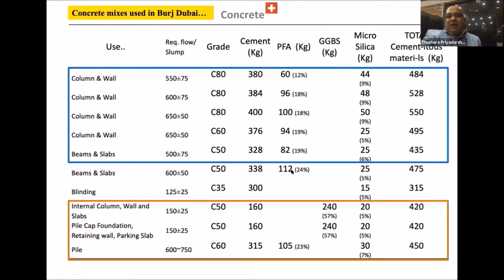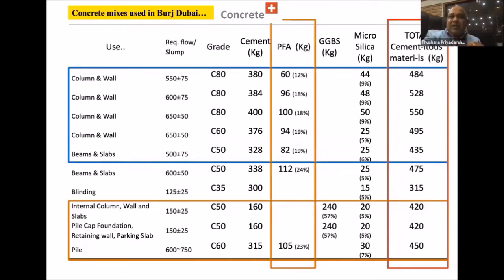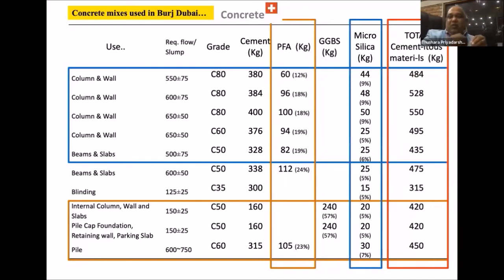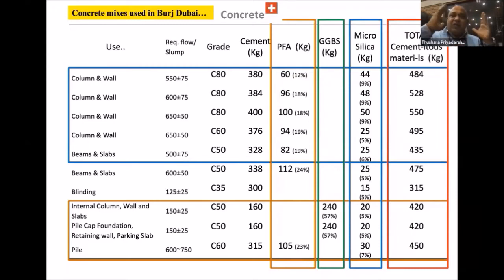So likewise, if you see the overall mix design of Burj Khalifa, this is part of the information. One thing you can see is the amount of cementitious material, not only cement, total cementitious material, they have maintained at 550. They didn't go beyond that because of durability. Then fly ash, 12 to 24%. Then microsilica, 5 to 9%. They have used it. And slag, 57%. I think this is a very good thing. As engineers, we should get it into our mind. So these are the ranges that we can move on.